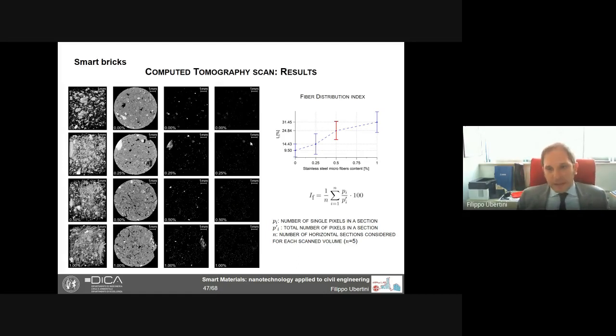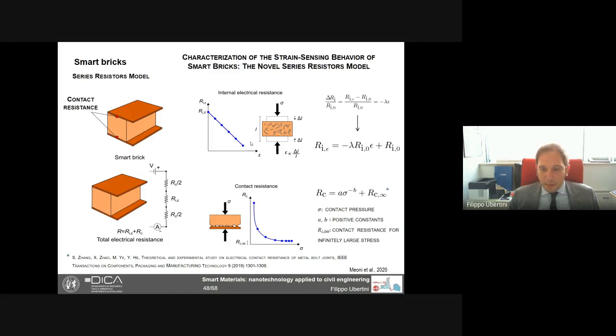By the way, these kinds of tomographies are very useful to ensure that the fibers are well dispersed, and we also compute a dispersion index to be sure that the composite is made properly. In terms of modeling these bricks, we have proposed a model that is a series of resistors, because we have some contact resistance that is also sensing, because the contact here is the plate electrode made of copper typically. And of course, this is going to be sensitive to the load, especially at low compression stresses. Then, of course, we have the internal change in resistance due to the piezoresistivity. So we have a model that accounts for the two phenomena through a series of resistors.